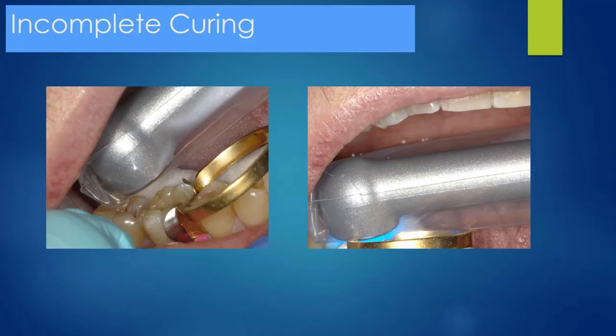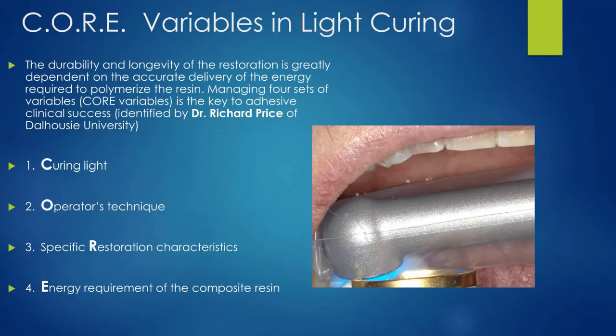We know incomplete curing is an issue. Holding the light too far away from the tooth, holding the light at a poor angle, not allowing the light to penetrate all the way down into the proximal box, not allowing correct angulation of the light so that a portion of the resin in the proximal box is never even hit with the light. This has long been an issue with direct resins, and many people don't test their curing lights, and certainly many people are not paying close attention to the positioning of the light, and very often we actually exceed the manufacturer's directions for allowable curing depths, and when that happens, we absolutely are compromising the composites that we're placing.